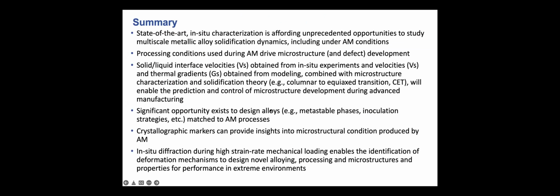A lot of opportunity exists to design alloys, for example, with metastable phases, like I showed for the Ti-1023, matched to AM processing in particular. I didn't talk about inoculation today. Crystallographic markers can show insight into the microstructure condition produced by additive, and maybe can be used for qualification and certification, in the example of Ti-64. And then in-situ diffraction during high strain rate loading allows us to identify the active deformation mechanisms and to design novel alloying, the phase stability or metastability, processing pathways, and also microstructures and properties for performance in extreme environments.